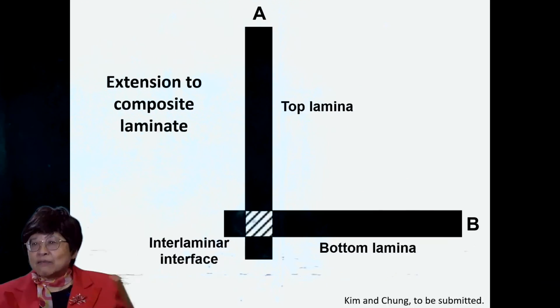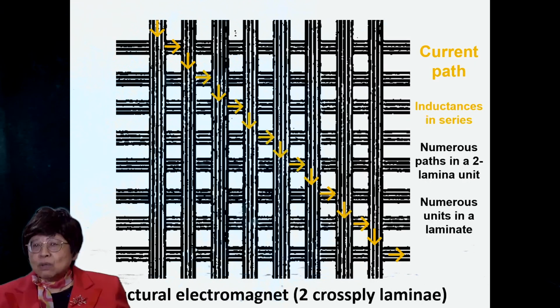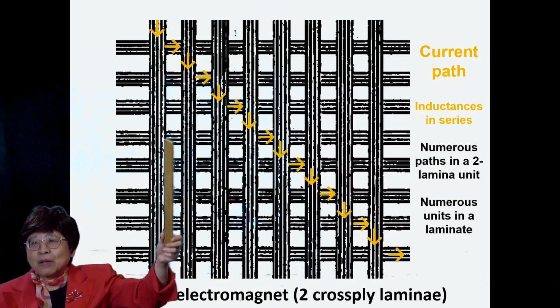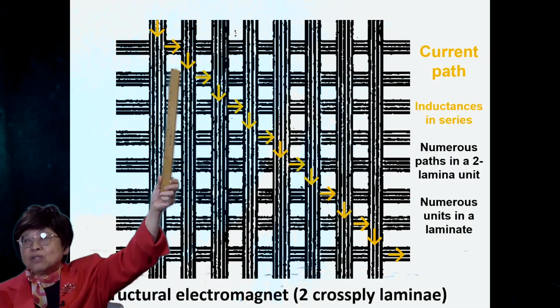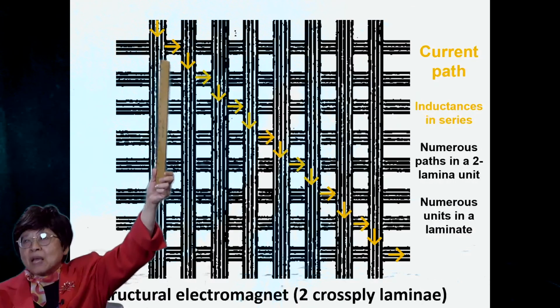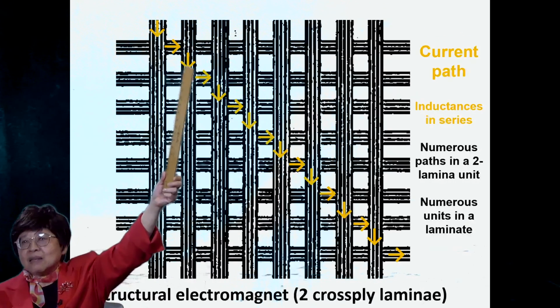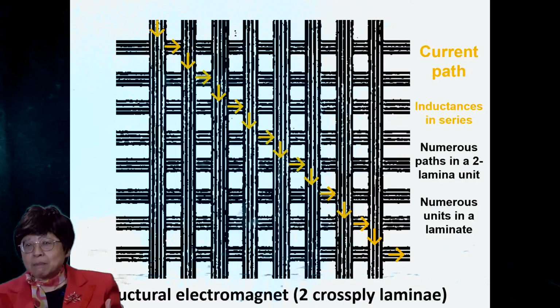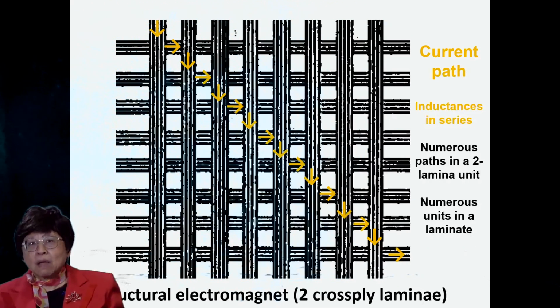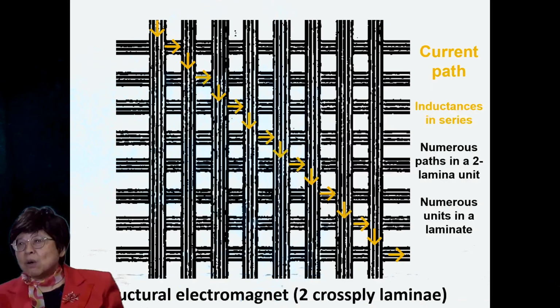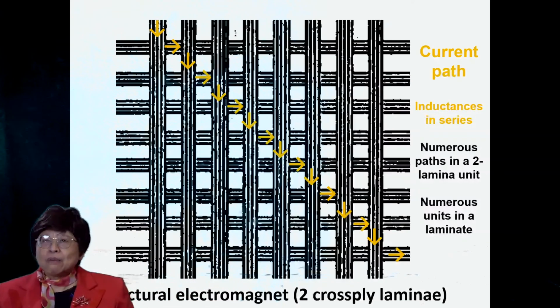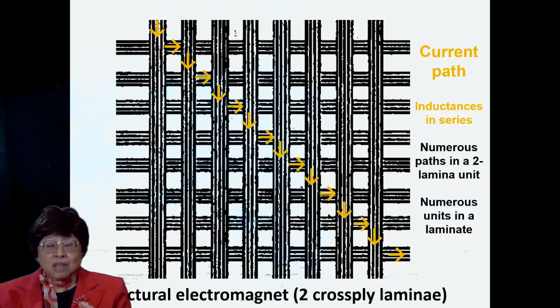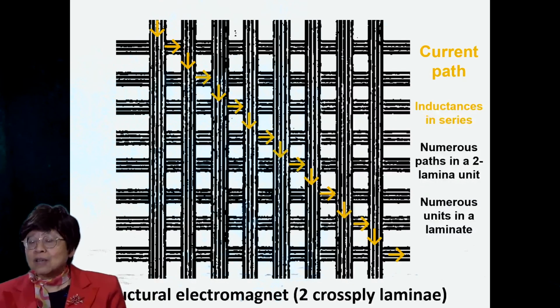So let's extend from this configuration to that of a composite laminate involving two laminae, the fibers in cross-ply configuration. So there are many interlaminar interfaces, and we have the current path shown by these arrows. So the current going like this between the top ply and the bottom ply, and also going through the interlaminar interface. So by having a current path like this, you are really having a lot of inductors in series, and so it's additive in terms of the inductance.